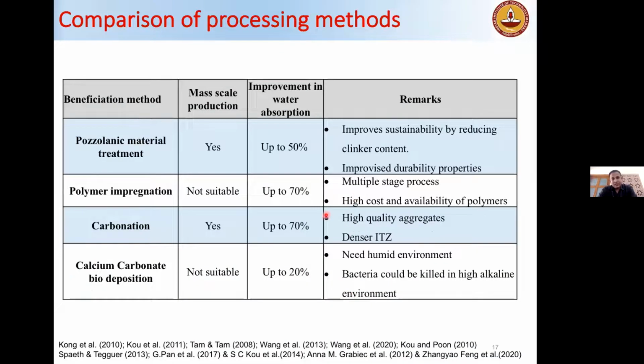So this slide is on the other type of beneficiation methods, where you are using pozzolanic material and PVA and carbonation. So we can see there is an improvement. Some are suitable for mass scale production, some are not suitable. So like if you see the polymer impregnation, the cost is very high, and this is a multiple stage process. Carbonation has a high quality aggregate. It improves the ITZs. And then you have the biodeposition, where you need humid environment, and the bacteria could be killed in high alkaline environment.